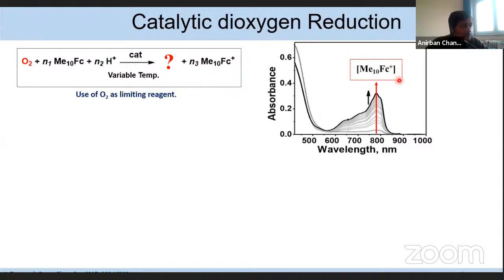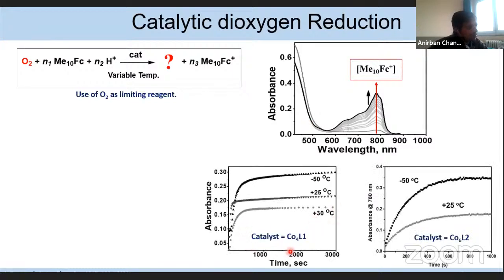From the known molar extinction coefficient value of the decamethylferrocenium, which is 520 mole inverse liter inverse at 780 nanometer, I calculated how much oxygen was reduced. But a very interesting thing here is that the oxygen reduction actually depends on temperature. I did the reaction at variable temperature. At low temperature, the amount of decamethylferrocenium formed is the highest, whereas with increasing temperature, the amount of decamethylferrocenium formed gradually decreases. And it is true for both the tetranuclear complex and the hexanuclear complex.